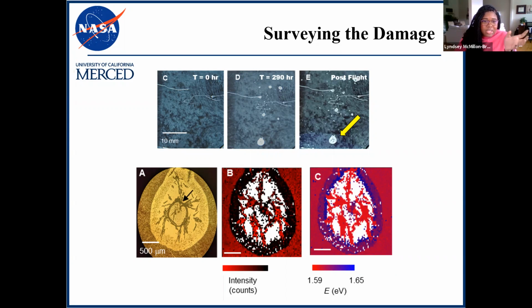And the rest of the film, however, and even some of those crystallites within the hole are still emitting. And when we take a look at that emission energy, which is shown in panel C, this reveals that whatever is emitted from that outer ring is blue shifted to the orthorhombic perovskite energy emissions. And the red emissions correspond to the energy level appropriate to tetragonal. So altogether from this defect, we learned that in this region, the edge is actually held to that orthorhombic phase, but the internal region is still tetragonal and it performs normally.